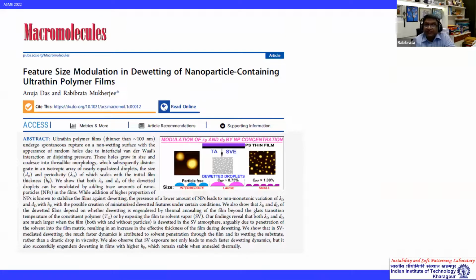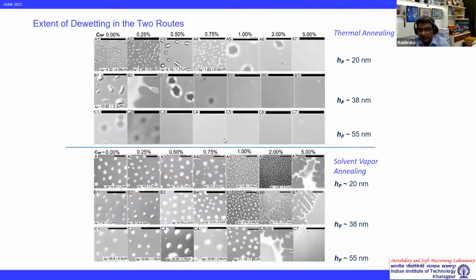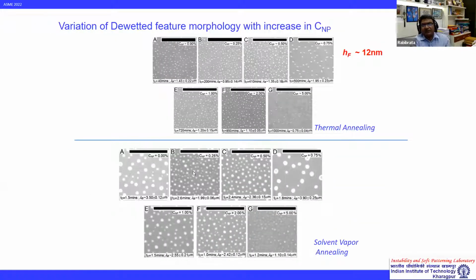There is also another interesting thing we found, which got no attention at all. Every paper which talks about this nanoparticle-mediated stabilization says the stabilization happens after a critical concentration of nanoparticles. So at lower concentration, the film still dewets. We were the first to look into what happens in these low nanoparticle concentration films, and we figured out that you can actually modulate the features. It also depends on whether you are following a solvent vapor mediated route or a thermal annealing mediated route. You can find the details over here, but for the benefit of time, I will skip these details.